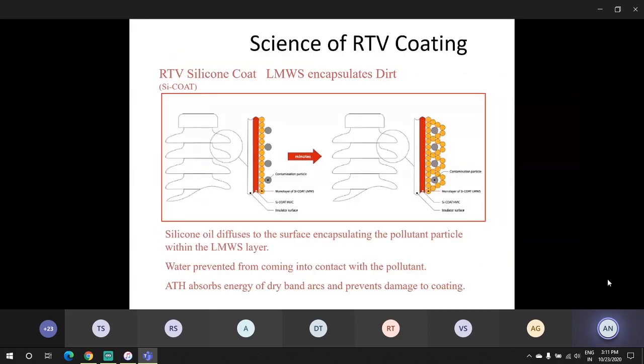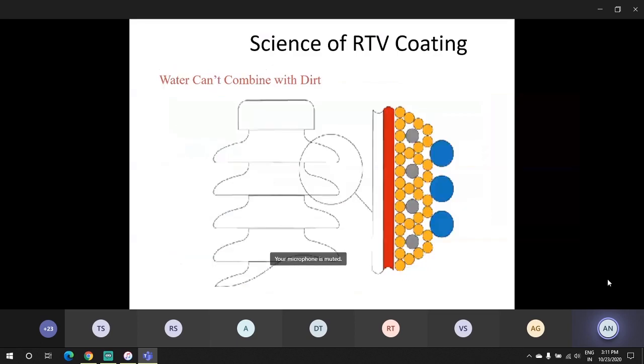So in short, the science of RTV coating is silicone oil diffuses to the surface, encapsulating the pollutant particle. Water is prevented from coming into contact with the pollutant. The filler, whether it is ATH or quartz, absorbs the energy of the dry band arc and prevents any damage to the coating. So this is the summary of the science. Water cannot combine with the dirt, and therefore the surface is kept dry, and there is no electrical discharge activity or corona activity on the surface of the insulator.